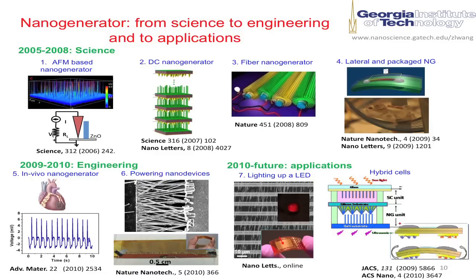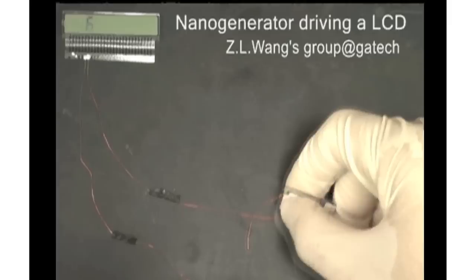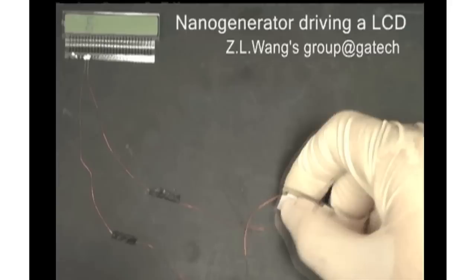Today we make the device about fingertip size, one centimeter square and 10 microns in thickness. We can generate continuous microwatt output, 10 to the minus 6 watt output. And if you store the charge in a little capacitor, you can output about 15 milliwatts. That's enough to drive a laser diode, drive a liquid crystal display. All conventional electronics can be driven by this little fingertip-size device.